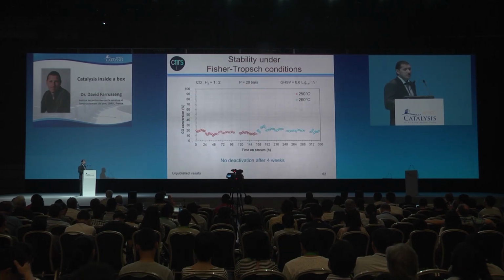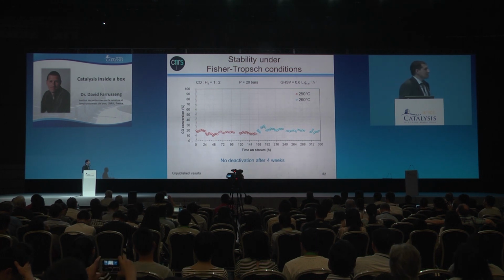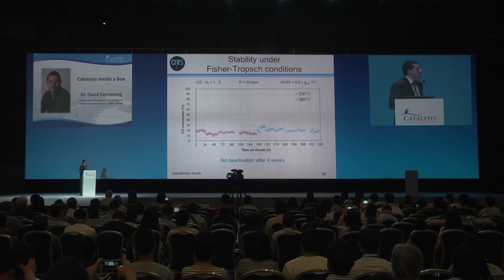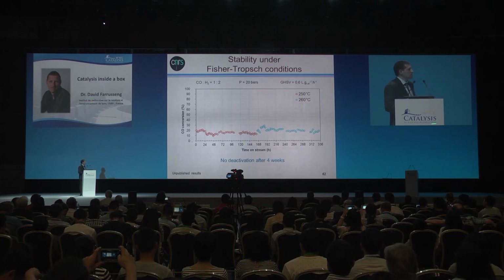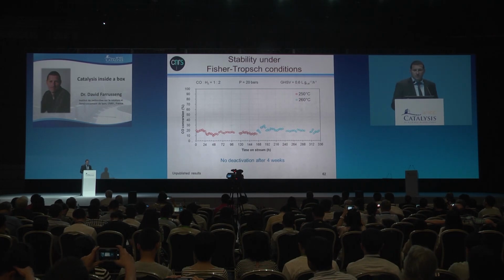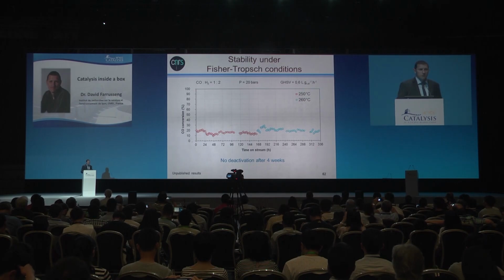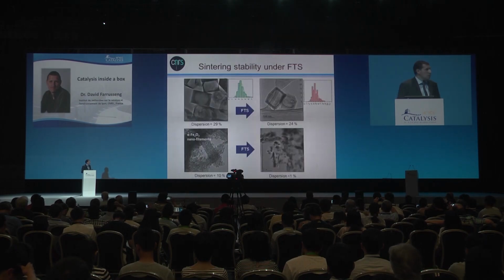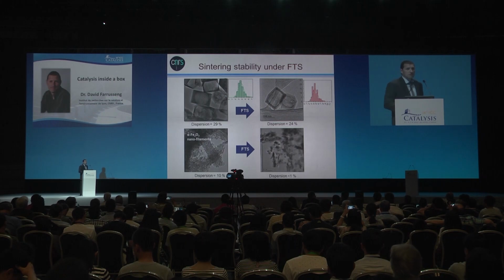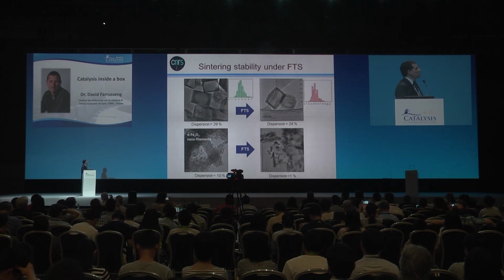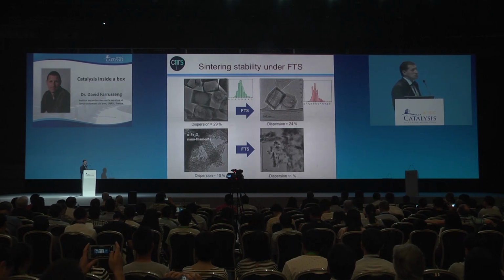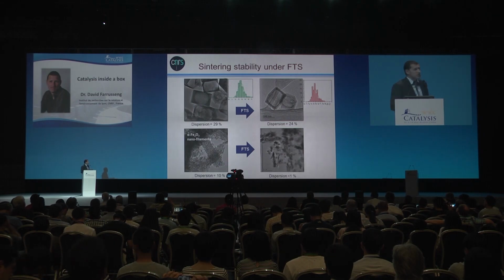So this makes these iron nanoparticles extremely stable in the Fischer-Tropsch conditions. We have tested that for weeks and even months under different operating conditions. We have analyzed by TEM the nanoparticles before and after, and you could see hardly any change of the size distributions of the iron, which is centered between 3 and 5 nanometers.